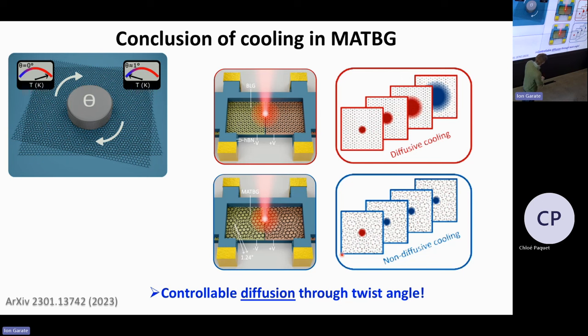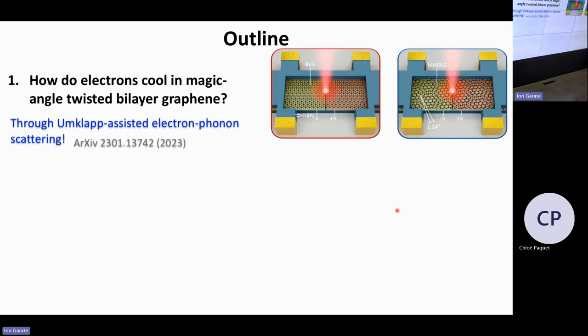Now, for the case of the twisted sample close to magic angle, what you see is that the cooling is so fast that actually there's no cooling spatially. So there's no spatial spreading of this heat. So you're also controlling the diffusion just by changing by 1 degree this sheet. So we thought that was quite interesting. So this is something that is under review for a bit too long, but okay. Hopefully it will come out still somewhere this year. So the answer is, how does this cooling happen? Well, through umklapp-assisted electron-phonon scattering through interaction with low-energy superlattice phonons.